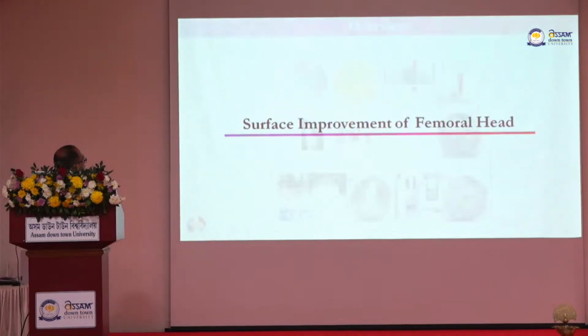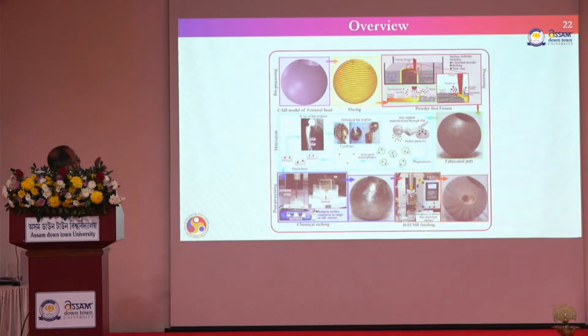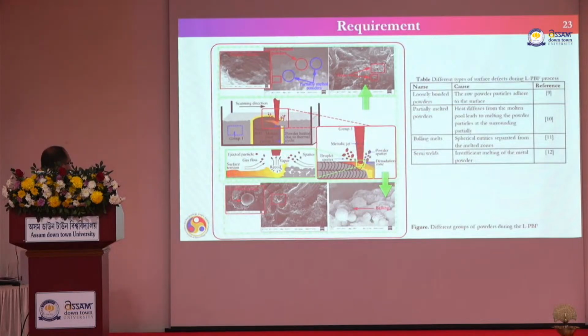So you can see this is the hip implant here, with spherical parts. Its surface finish, which is developed by the additive manufacturing process by layer deposition, was rough. So after that we did chemical etching. After chemical etching, its surface roughness is reduced to less than 1 micron. After that we did hybrid electrochemical magnetorheological finishing and received this kind of mirror finish surface. These are the different defects when fabricating any components using the additive manufacturing process. This kind of balling effect will be there, and loose metal powders will be there. These things have to be removed by our finishing process.